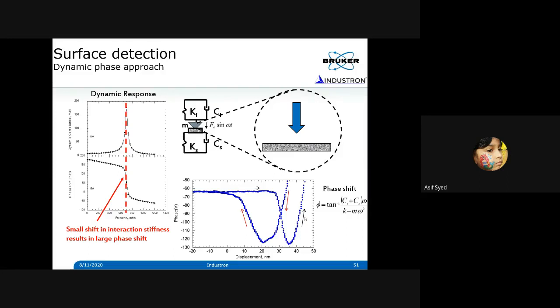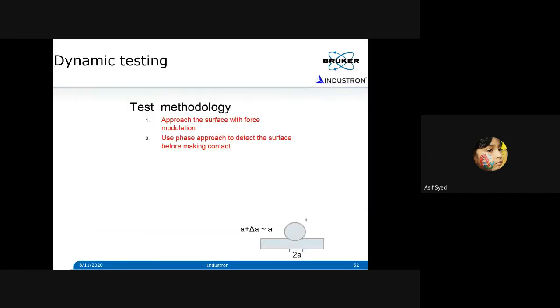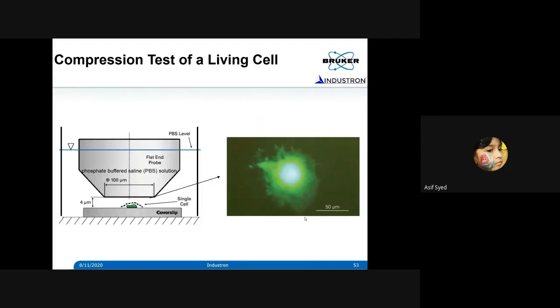So measuring the phase shift is a very sensitive way of sensing the surface, and using that, you can do a lot of good things. One thing that I would like to show you is how you can do a compression test of a living cell. Using a fluorescence microscope, which comes with the instrument when you buy the fluorescence microscope option, you can put a biomarker, you can see the cell, and if you use a very flat-ended tip, in this case about 100 micron, you can bring the tip into alignment with the cell that you want to test, and then make contact.